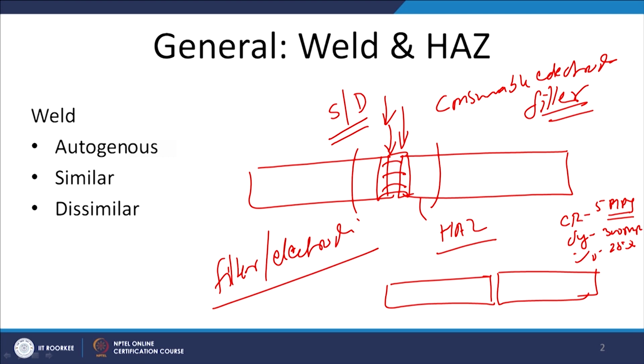So, if we want our weld metal to have much better properties, then accordingly we can choose the suitable filler metal or electrode offering much better corrosion resistance, like 5 MPY, yield strength of 500 MPa, and percentage elongation of 30%. So, this kind of flexibility is available to regulate the weld metal properties, at least with the consumable welding processes, or those processes where we can choose the filler metal of either similar or dissimilar composition.